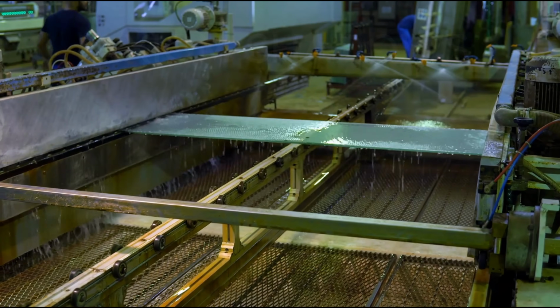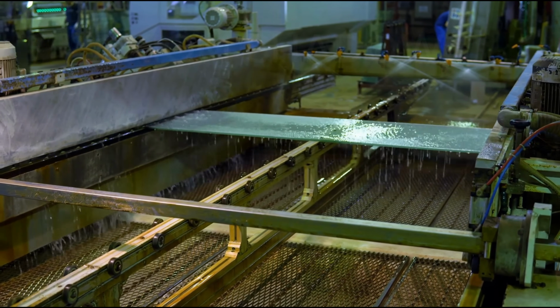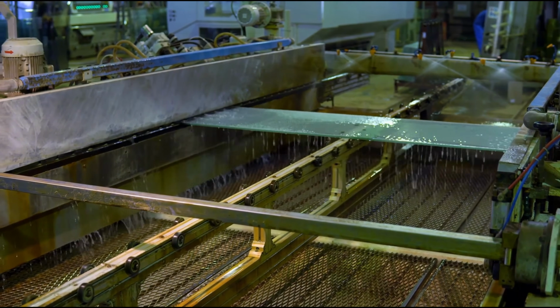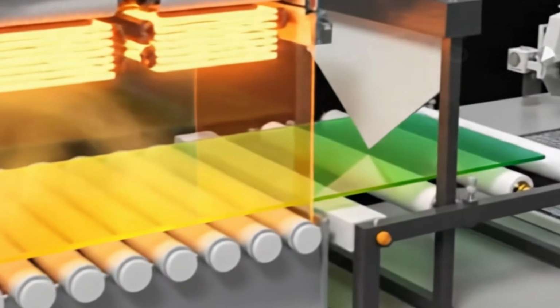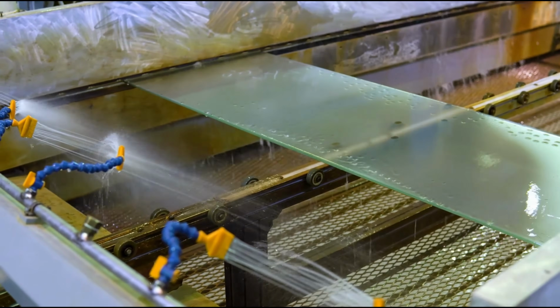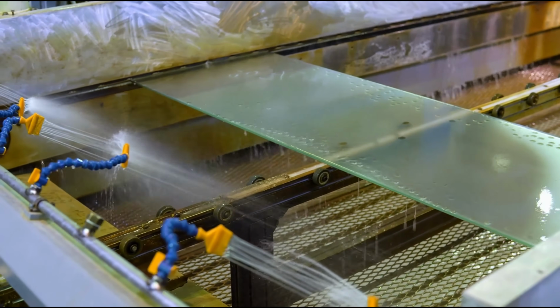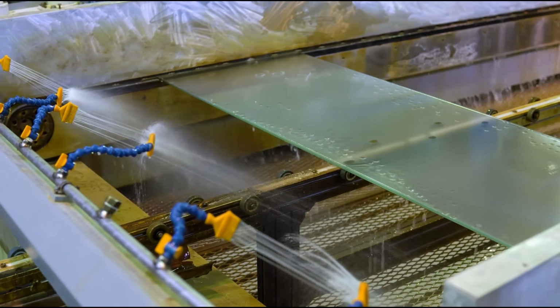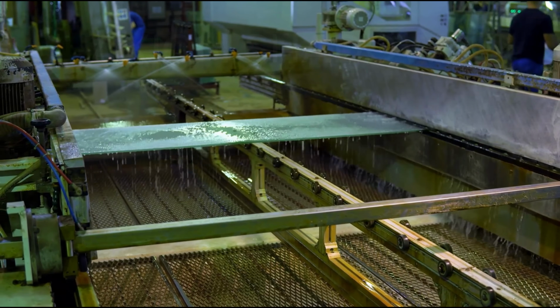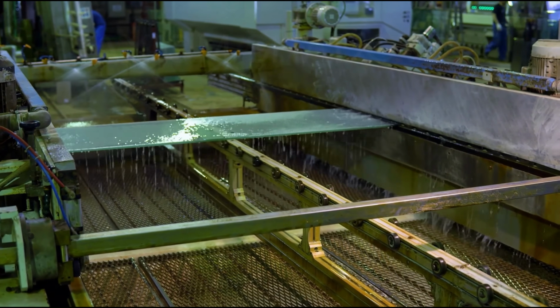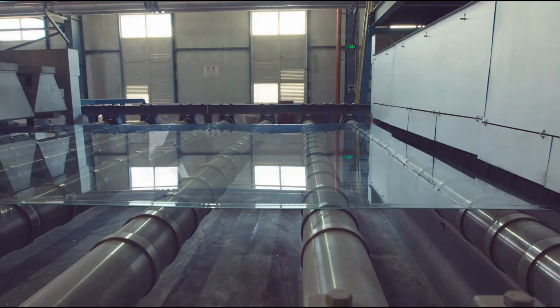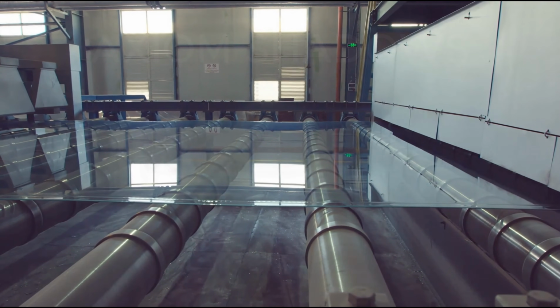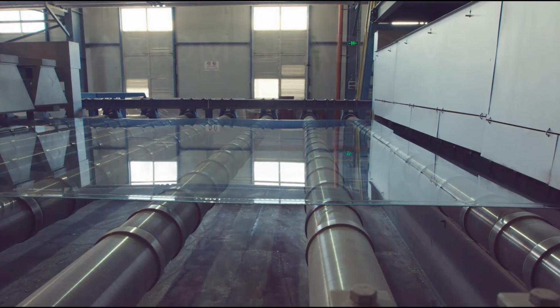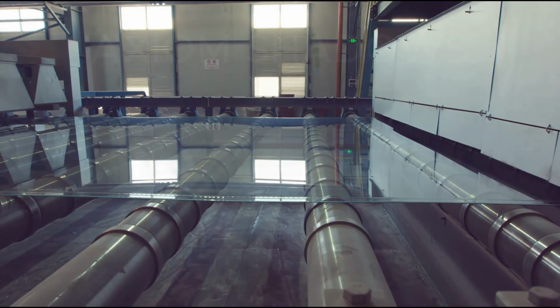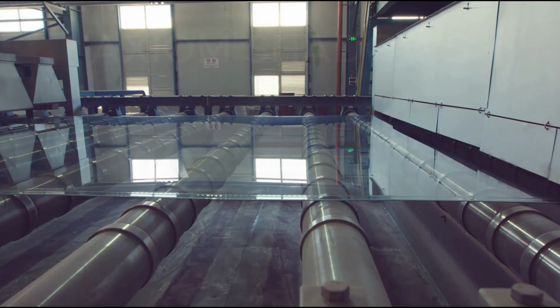If you cool glass too quickly, it shatters. So it must pass through the annealing zone, a long tunnel where temperature drops gradually from 600 degrees Celsius to room temperature. This slow, even cooling relieves internal stress and prevents warping. This process takes anywhere from 30 minutes to several hours, depending on the thickness. At the end, the once molten river emerges as a flawless sheet, clear, flat, and ready to be transformed.